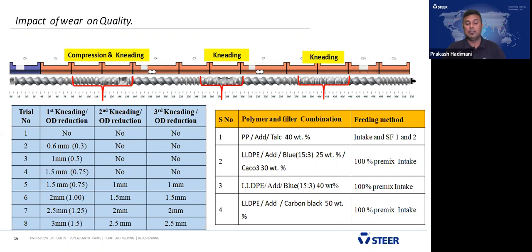We did OD reduction, and 1 millimeter OD reduction for the first kneading section, that is 0.5 millimeter each side. In the third section also 0.5 millimeter per side. At the sixth level, 2 millimeter OD reduction means per side 1 millimeter in the first kneading section, and in the second kneading section 1.5 millimeter on both sides. That shows 0.75 per side of OD reduction. It is similar in the third section also.